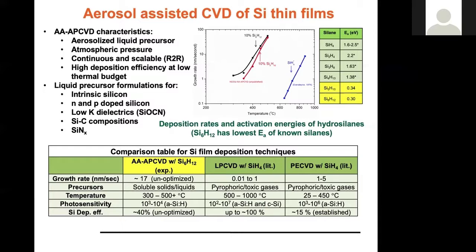In the table below, I want to highlight some of the differences in growth rate. We see a non-optimized growth rate of 17 nanometers per second. Compared to traditional chemical vapor deposition, that's anywhere from 1 to 3 orders of magnitude faster. Even with a newer technology like PE-CVD, it's anywhere from a factor of 3, maybe as high as 10 with a fully optimized process, faster.